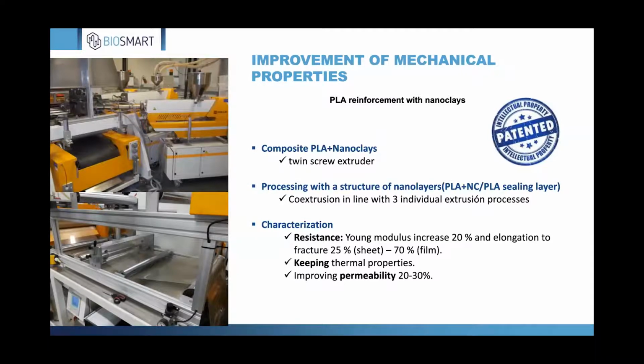Then we have been implementing the PLA with nanoclays. This is a patent from Idener, is partner in the project, and we have applied this PLA with nanoclays using a twin extruder, using a 3-step extrusion process, co-extrusion in line, and using PLA, the PLA with nanoclays, and also PLA sealing layer. As a result of this structure, we have increasing the Young's modulus by 20%, the elongation to fracture by 25% in sheet, and 70% in film. And it is possible to keep thermal properties, improving permeability between 20 and 30%.